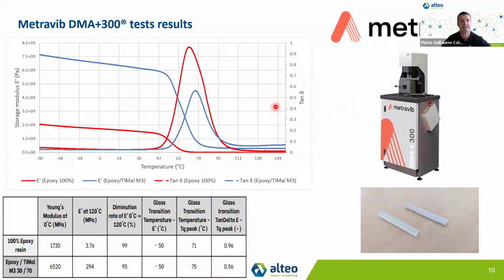So here we can clearly see the storage modulus, which is plotted, and tangent delta versus temperature increase. The filled product shows that the storage modulus is much higher when the epoxy is filled. So ATH acts as a reinforcement agent. We can also see that the tangent delta could be used as a glass transition temperature determination. That's one way to measure it. The other way is also to take the Tg onset, which equals a slightly lower Tg.